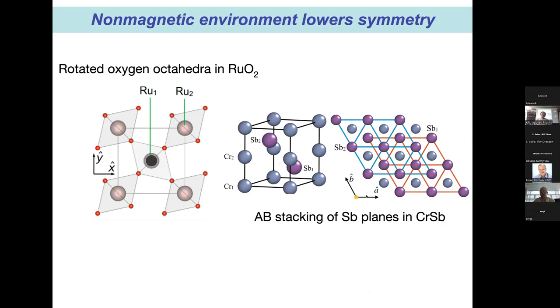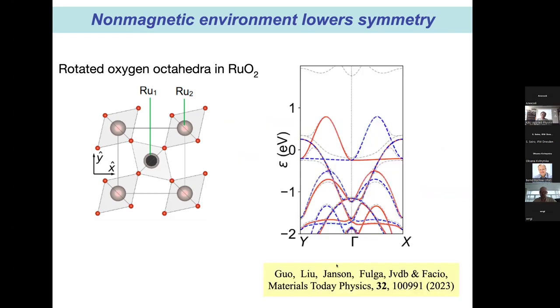Another one is chromium antimonide. It's a more complicated system. It's triangles of antimony atoms separated by triangles of chromium. And because of the stacking of these triangles, you get the same kind of altermagnetic situation, which is not so easy to see here. I take this now from our paper, where you can calculate the spin splitting, and you see here, if you go from gamma to X, then there's some spin up band separated from the spin down. And if you go 90 degrees rotated from gamma to Y, it's the other way around. Yeah, you see, this is typical for an altermagnet.